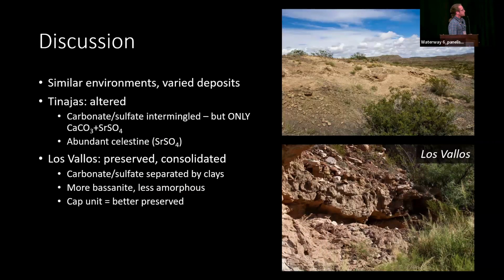What does it mean? So we have these 2 deposits that formed in nominally similar environments, but came out very differently. And this is possibly due to the climate differences between them, that Tinajas was laid down in a much cooler, wetter environment. Maybe it was less well preserved because of that. But it's also possible that the Tinajas underwent a good bit of alteration after it was laid down. We see this intermingling of carbonate and sulfate. Again, calcium carbonate with strontium sulfate, not the 2 calciums together. And we see this abundant celestine, which is a weird mineral to find.